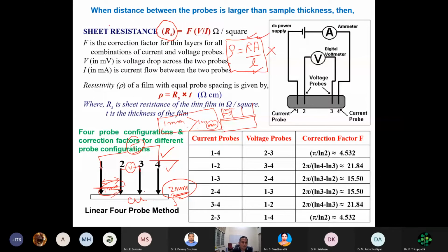So what I am supposed to do is apply some correction factor. Those correction factors are given here depending upon the probe combination. So my sheet resistance will have a formula F into V by I. V is the voltage drop, I is the current. Generally in measurement, we apply a known current, 1 milliampere, 2 milliampere, by using a source meter. We measure the voltage drop. So if you take V by I, you should get a resistance.